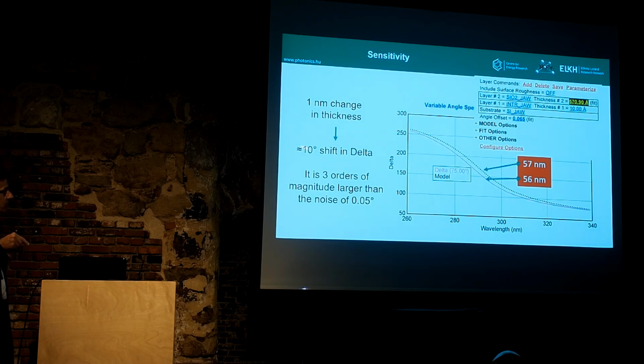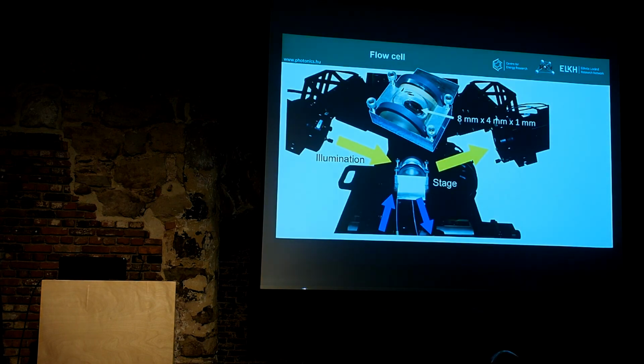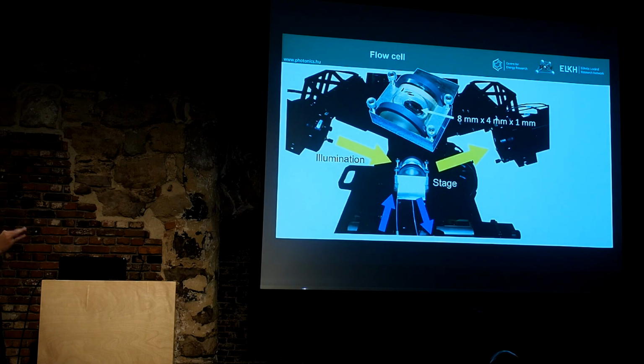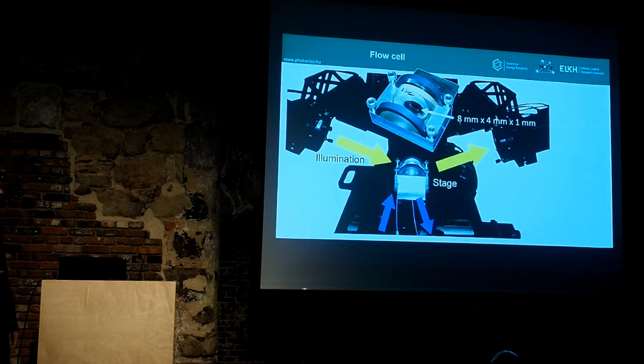So the change here is approximately 3 orders of magnitude larger than the accuracy of the measurement. This gives you a feeling of the sensitivity, because we only changed 1 nanometer here. So we have a non-destructive method, which is very quick. Such a spectrum can be measured in 1 second. So what can we use for this method? And I only have 3 more slides to show you some examples.